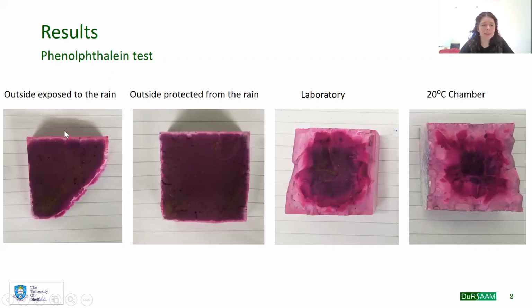And we can see that for the sample outside, the carbonation front seems to be the same as the oxidation front, even though it's really hard to tell because of the dark color of the sample. And for the sample inside, we can see that the carbonation front seems to be equal to the light gray area, the white area, not the dark gray area.